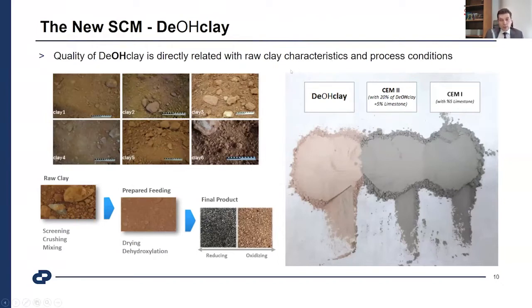When we look at quality, as you can see, there are different types of clays taken from the field, with different colors, compositions and physical characteristics, and especially high quartz content with this type of material. The process is based on screening, crushing, and mixing together for a homogeneous formation of raw clay, then prepared feeding, drying and dehydroxylation, and then the final product is taken out.